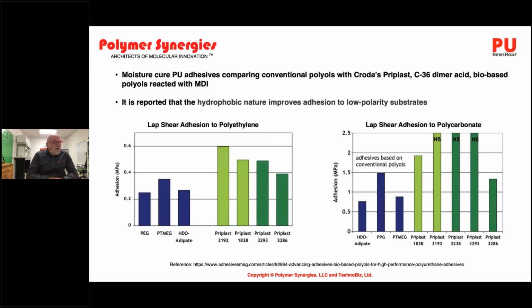Here are some moisture-cure polyurethanes comparing conventional polyols with Croda's Priplast C36 dimer acid polyols. They've been reacted with MDI. We can see that they're comparing their Priplast polyols with conventional PEG, PTMEG, and hexanediol adipate polyols. You can see that lap shear adhesion to polyethylene is very good, and to polycarbonate it's very good. It's reported that this good lap shear to these low polar substrates has to do with the hydrophobic nature of these C36 dimer acid backbones that they're using to make these polyols.